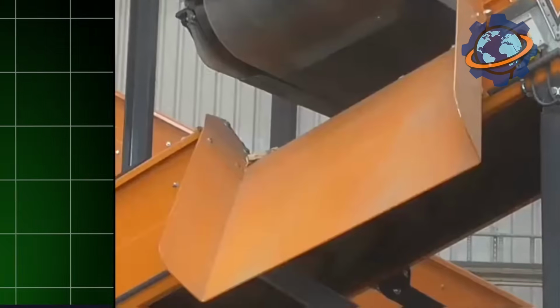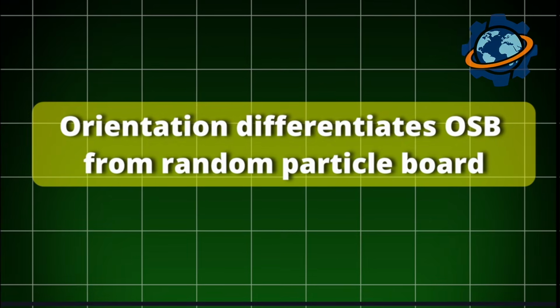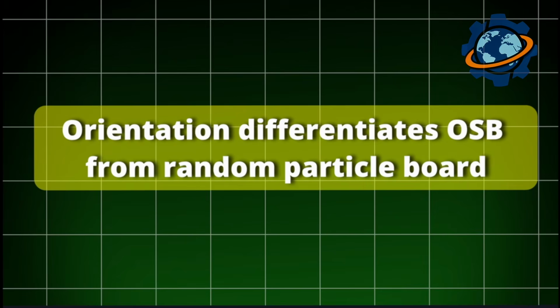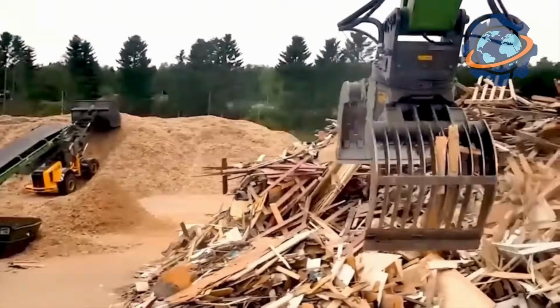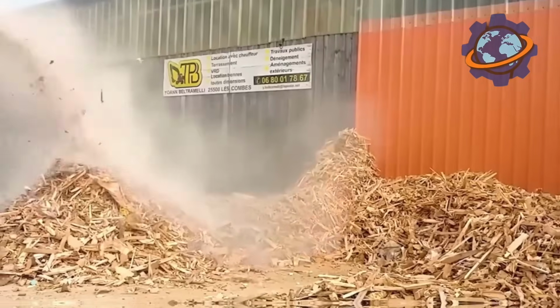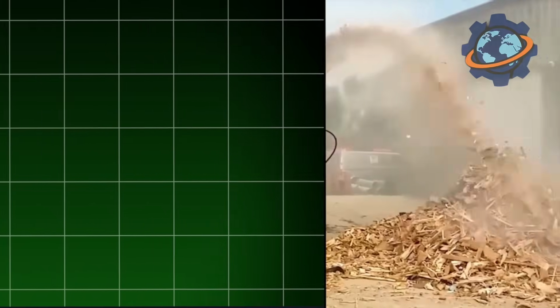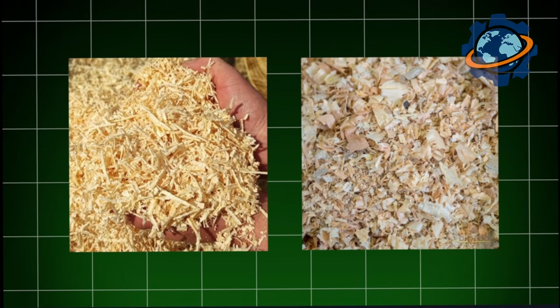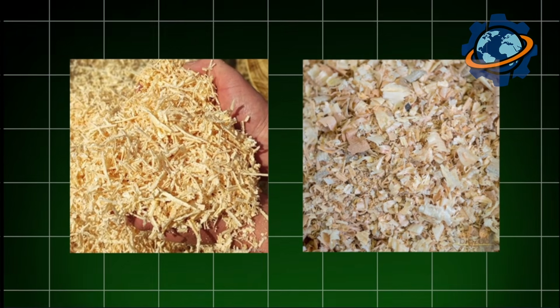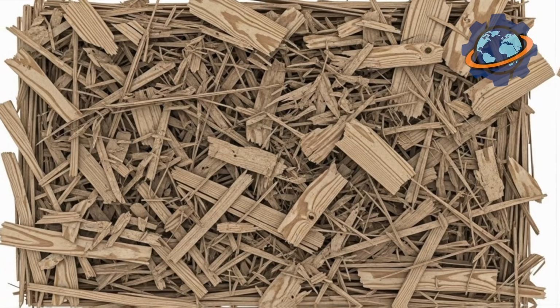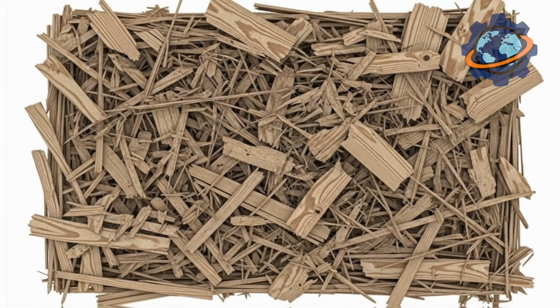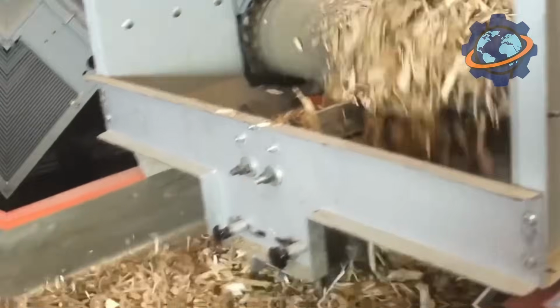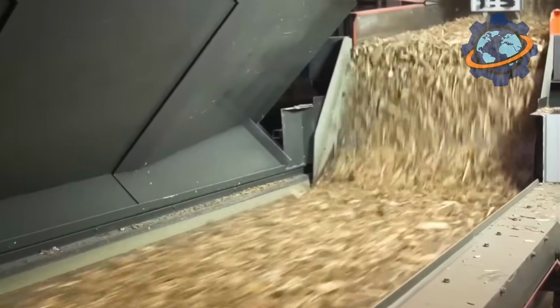Orientation. Orientation differentiates OSB from random particle board. The forming line uses electrostatic alignment or mechanical orientation systems, forcing strands to lay parallel in outer layers, perpendicular in the core layer. This mimics plywood's cross-grain structure but achieves it through chaos rather than precision. Picture billions of wood strands, each finding its place in a 3-dimensional puzzle.